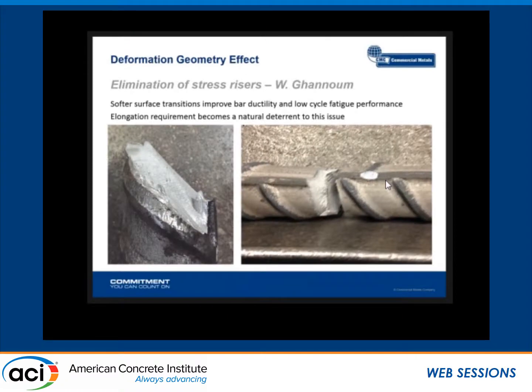Now here's another look at it, and this is a little bit of airing some dirty laundry here. This is what happens when the base of the deformation is too sharp. The bar breaks right along the base of the deformation, but what this also illustrates, at least compared to the bamboo bar, is that it's not as bad. If the bar is bamboo, it would break even sooner with even worse ductility. Now in this case, we made this change in direct response to Dr. W. Ghannoum's research on low cycle fatigue. We realized this was a problem, so we made changes to the geometry and we got the bar to go straight across instead of following the deformation again.